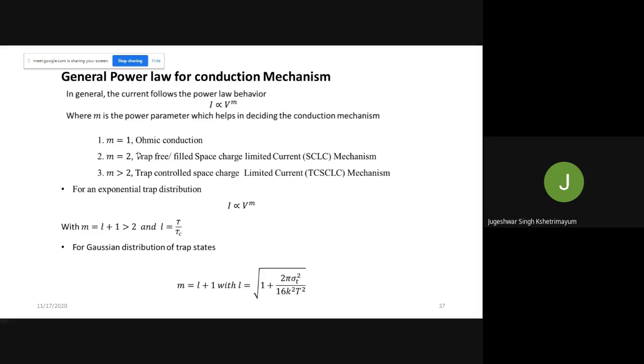It's like this. When you plot for V equals I to the power m, if m equals 1, then I is proportional to V. This is nothing but ohmic contact. If m is equal to 2, then it is trap-free or filled space, meaning there is no control from the traps. When m is more than 2, we found that some trap is controlling the conduction, meaning we are not filling things completely, or something is stopped by the traps. Okay, so these are for the power law conduction mechanism, from which we can identify which model I have to choose by seeing my experimental results.